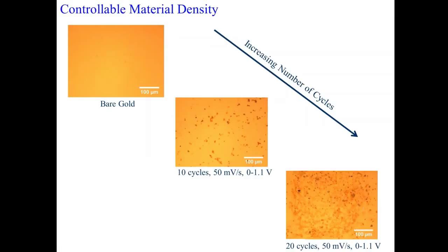However, if we control the density and the number of cycles, we have a variation in the roughness as well as the homogeneity of this film. You can clearly see here that the more material we deposit, or even higher concentration, the more agglomeration we observe with the film coating itself.